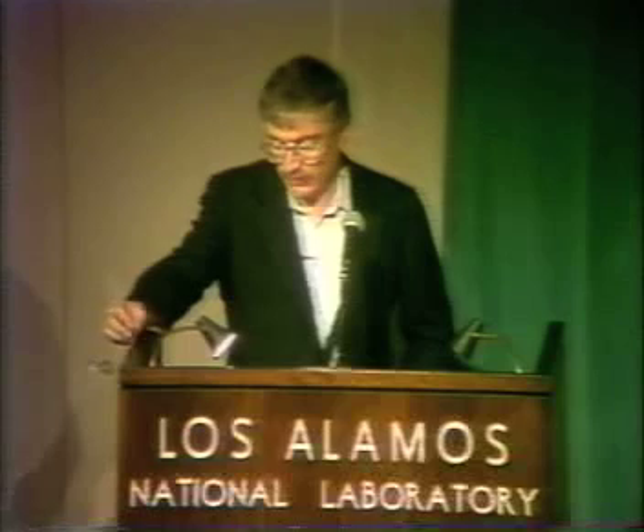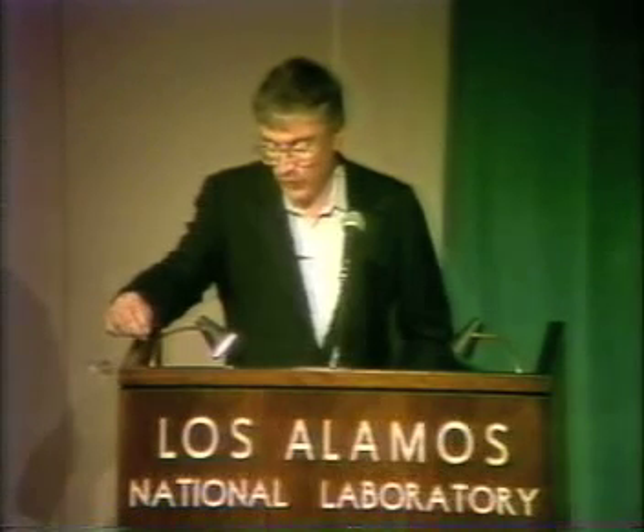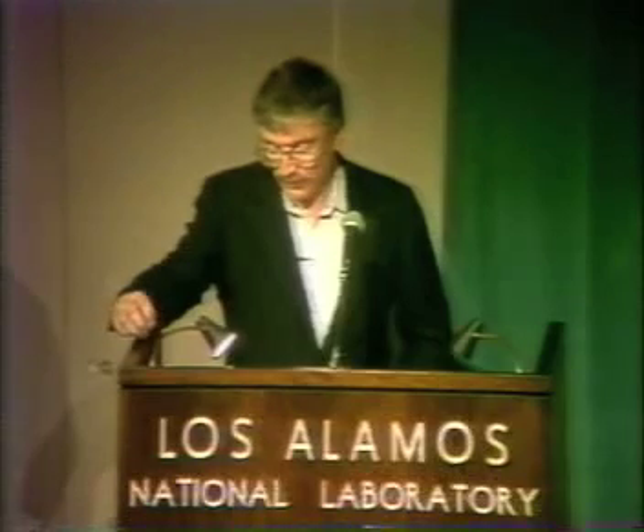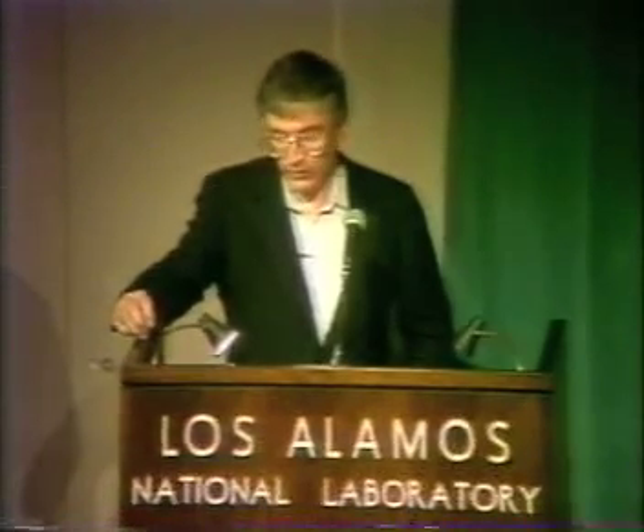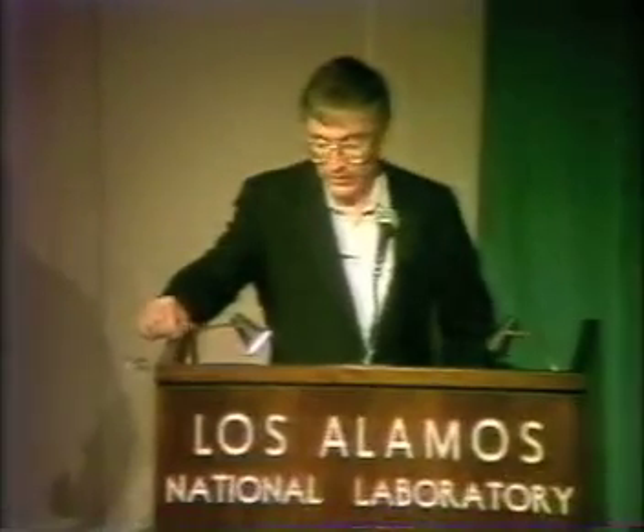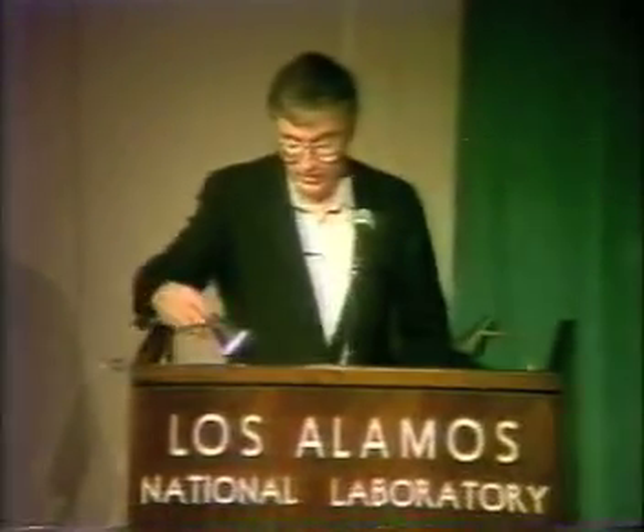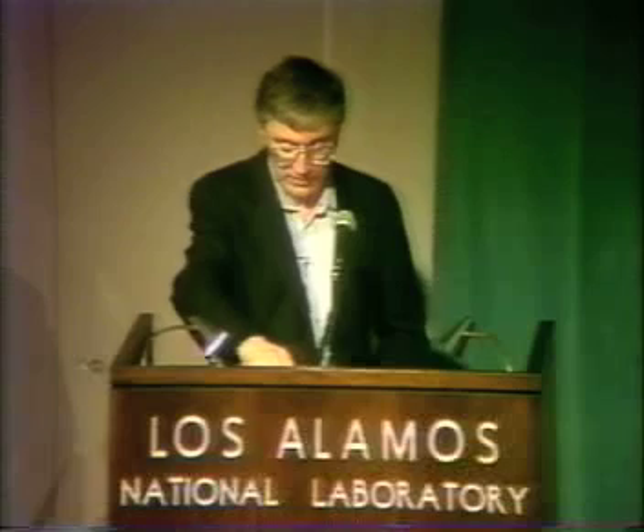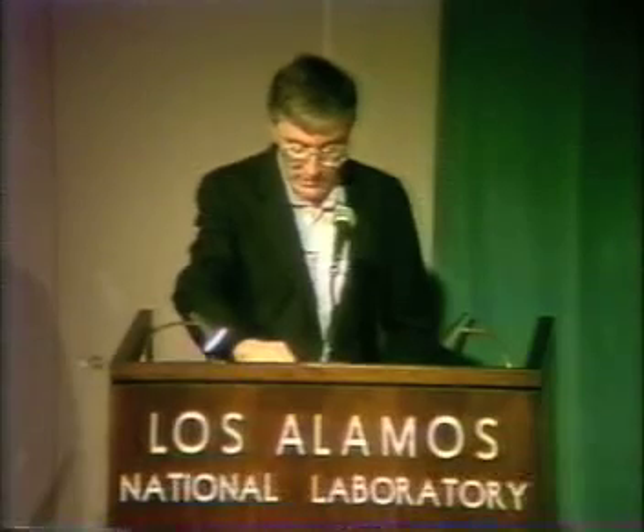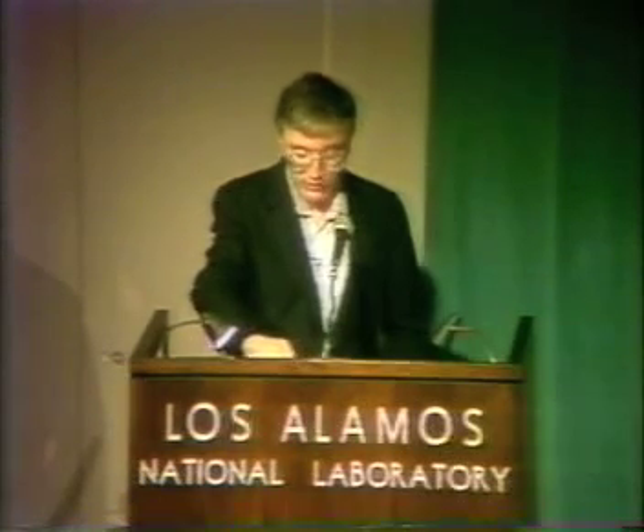A further thing they predicted was that the rate of reaction between protons and deuterons is almost 100,000 times faster than the deuteron-deuteron reaction in their scheme. They have a scheme of shielding by a heavy electron of effective mass 10 times the normal electron in that lattice. We did not do anything quantitative on it, but we did try in January to get a blank experiment with a palladium electrode that we knew worked in regular water, and we did not get the heat in, heat out balance that we had expected. We did get some excess heat.